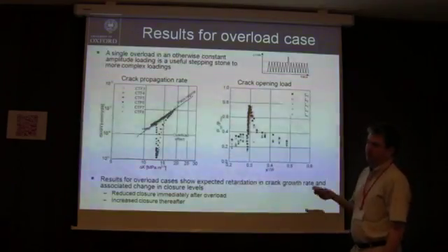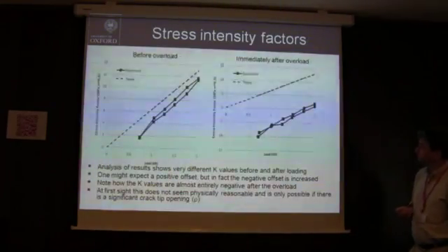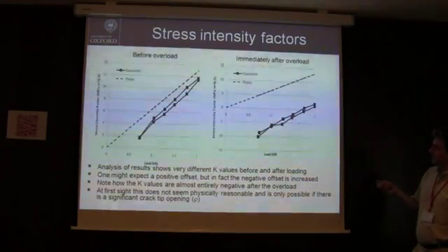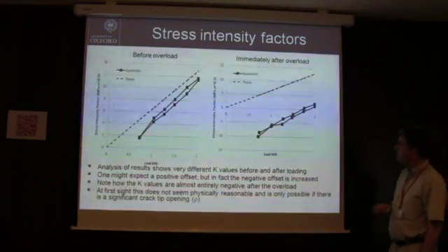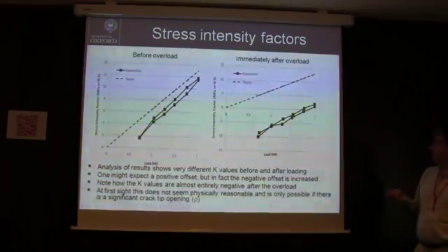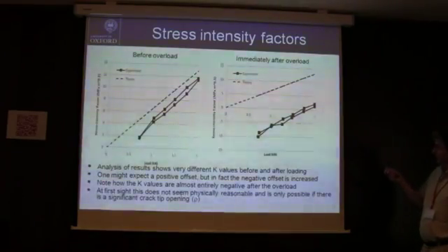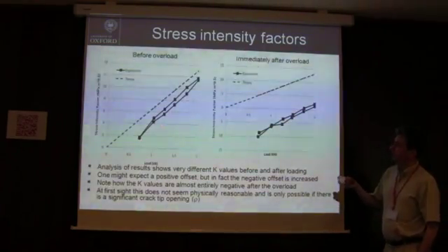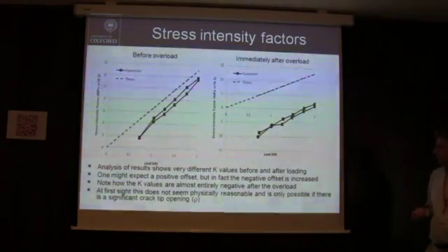How does this pan out when we look at displacements? Okay, well here we are, here's the results before the overload, so you can see this is pretty much what we had before. Here's the theoretical line, this is our experimental line, a little bit of hysteresis, so we've got loading and unloading here, and a small kind of offset. Immediately after the overload, this is what you get. So again, this initially looks pretty similar to this, but with a larger offset.